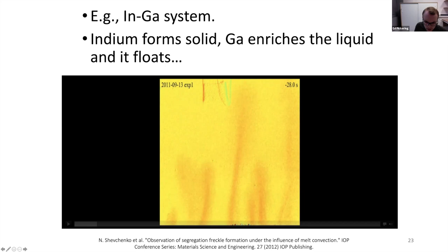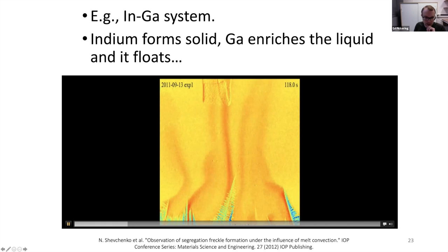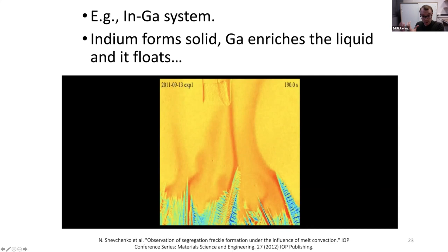So we're about to see some dendrites of indium poking out. And as the indium's forming, it's rejecting gallium into the liquid, and that liquid, which appears red here, is then floating quite beautifully. And you'll see as it comes in from the bottom that we have some dendrites of indium there, and they're ejecting this, enriching all the solute into the liquid. That's enriching the liquid, and it's making the liquid float in this particular case. So really a brilliant example of this